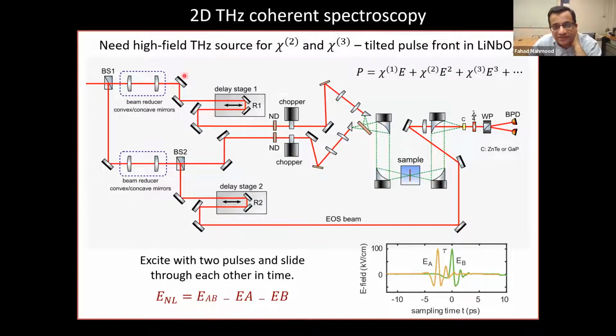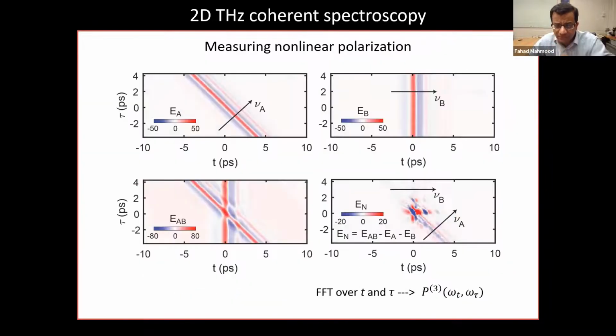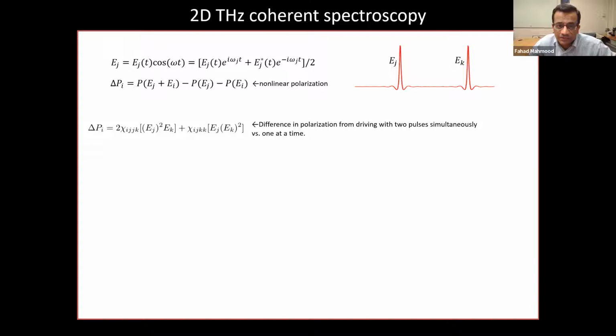I'm not going to discuss the details of the setup here, but the main thing about the setup is that you need very high field sources of terahertz because you want to couple to the higher order susceptibilities, which are orders of magnitude weaker than your linear susceptibility. And so you want to send in two very strong terahertz pulses with field strengths on the order of hundreds of kilovolts per centimeter. And then you want to essentially extract the nonlinear susceptibility out. Okay. I'll skip over this because I just want to introduce exactly what we're measuring.